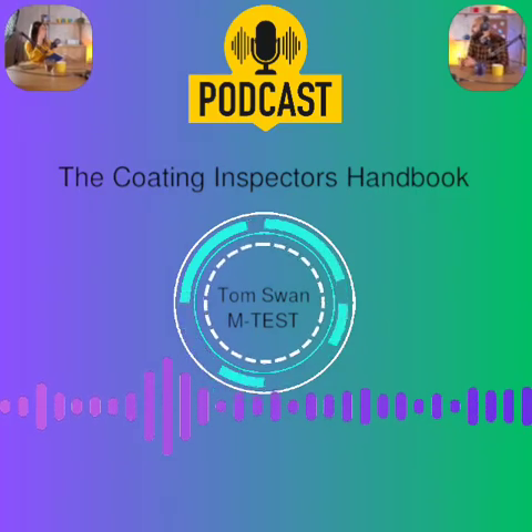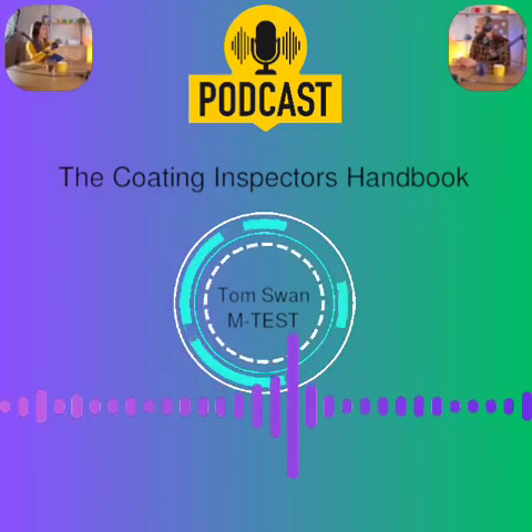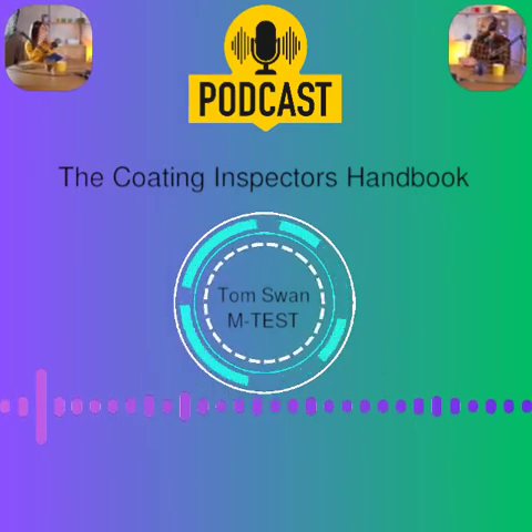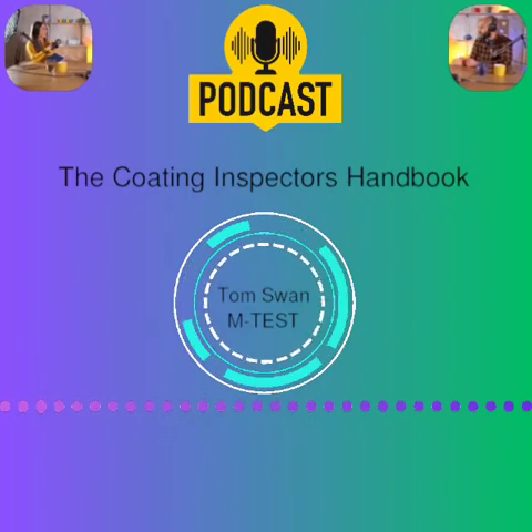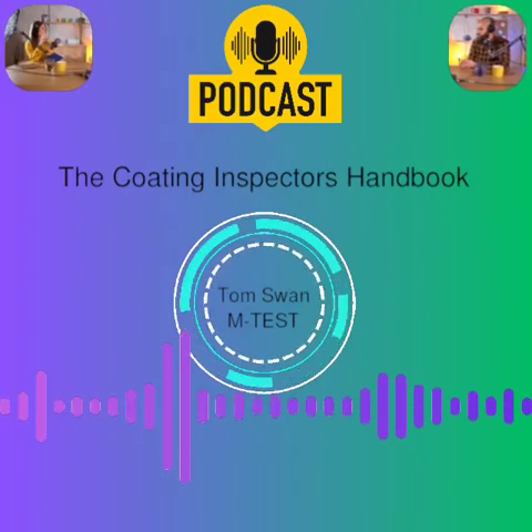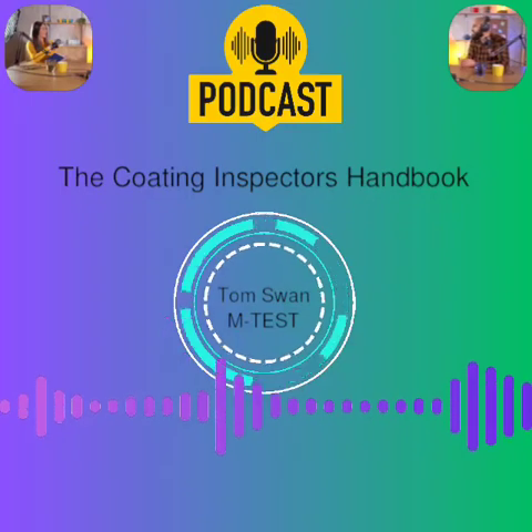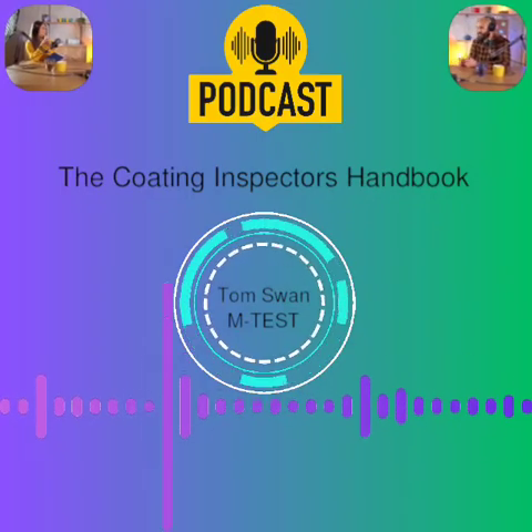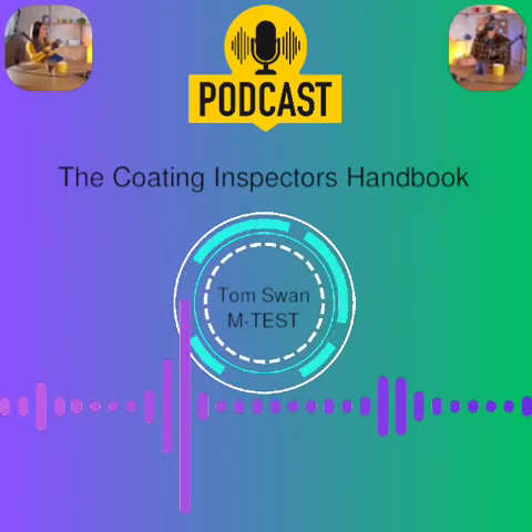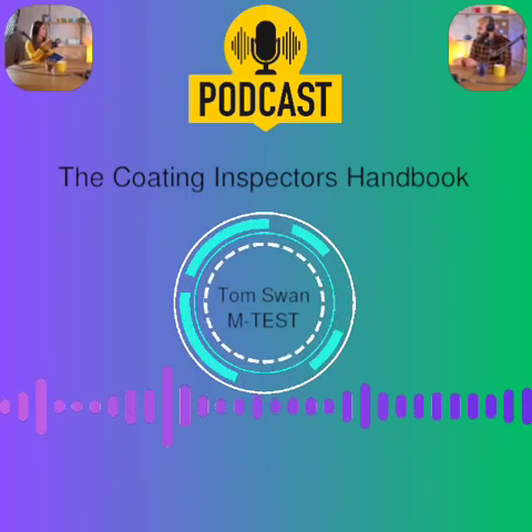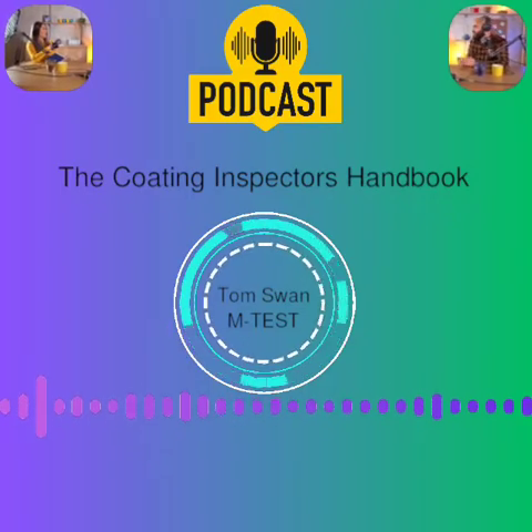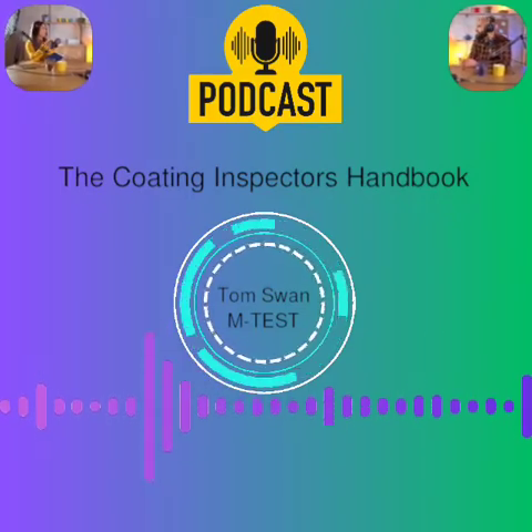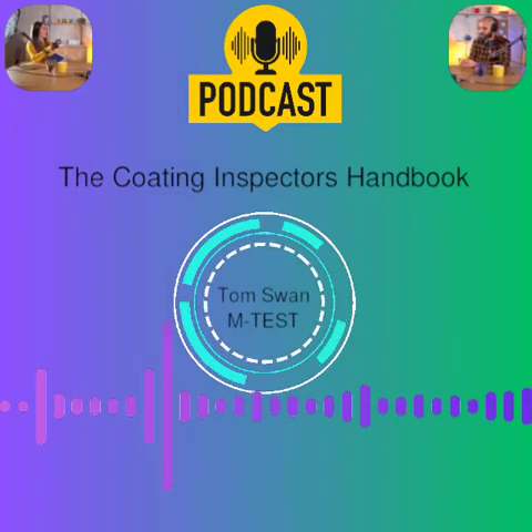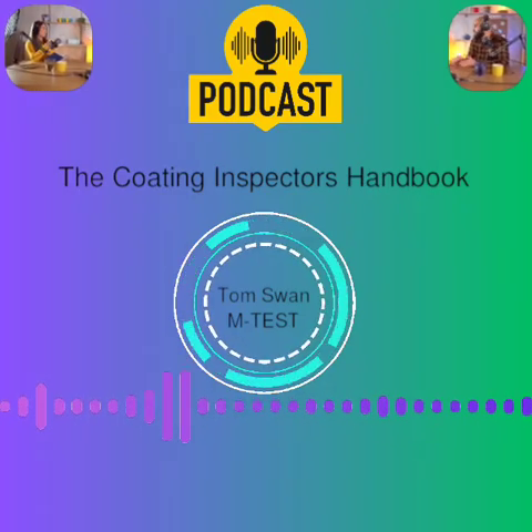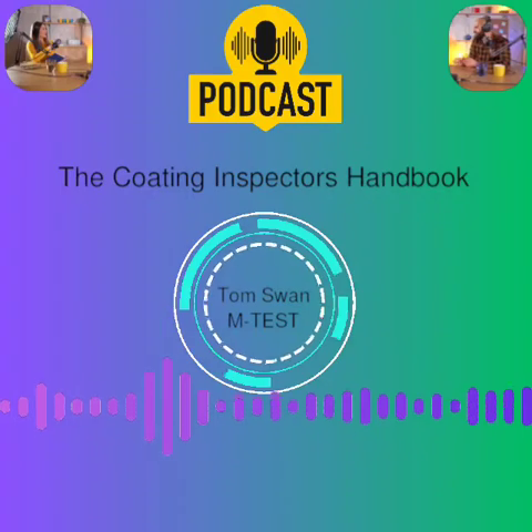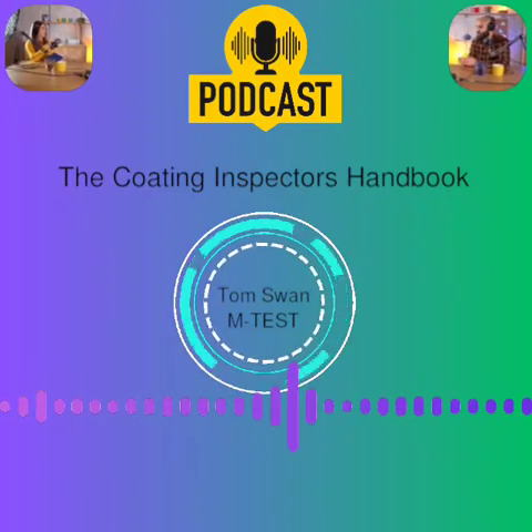Okay, let's move on to testing the paint itself, starting with wet film thickness, WFT. Right, WFT. Measuring the paint thickness right after it goes on while it's wet. Who does this usually? Primarily a contractor QC check. Allows them to adjust their spray technique, gun settings, thinning before it dries. Inspectors should verify it, though. And you can calculate the target WFT you're aiming for. Yep. Simple formula. Target DFT over percent solids by volume. Or with thinning, WFT equals DFT times 1 plus percent thinner, over percent solids. Get the solids and thinner info from the PDS.